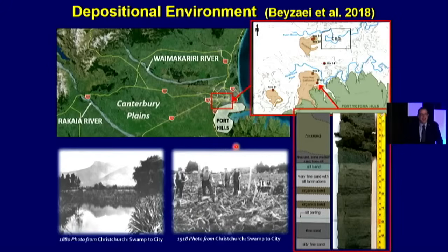And so it's back to the geology. Christine looked at the 1850 maps and saw that the sites that did not exhibit ejecta were in these backwater swamp areas. In fact, for Christchurch, there's a book called Swamp to City. This is what Christchurch looked like. And so these swamp areas are the areas that have these layered materials. This is important to do.